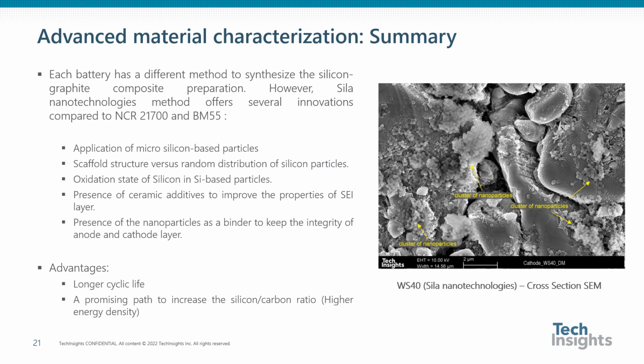In summary, we concluded that the anodes of these batteries were synthesized using different methods, most likely ball milling for NCR21700 and BM55 cells. With respect to WS40, the results reveal several innovations compared to NCR21700 and BM55, including application of micro-silicon-based particles, as we know, smaller is better. A scaffold structure versus random distribution of the silicon particles. In fact, the silicon particles are connected through a network.